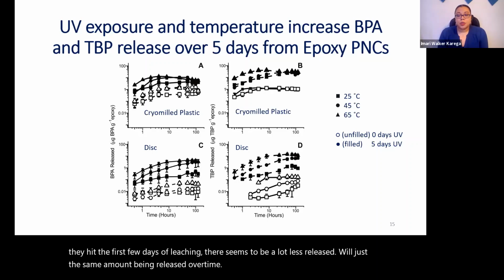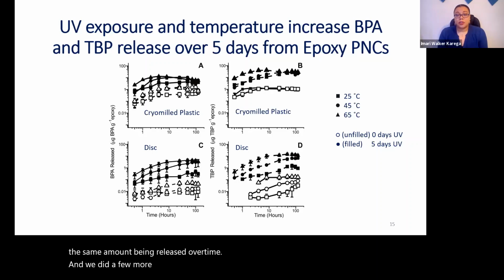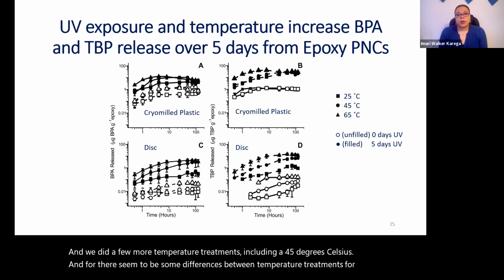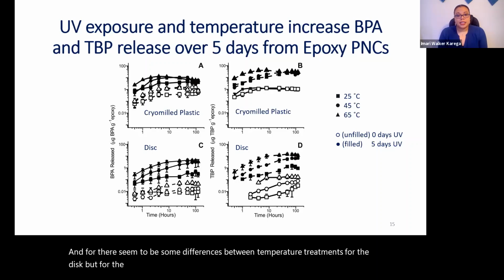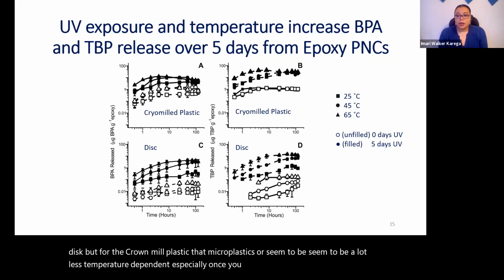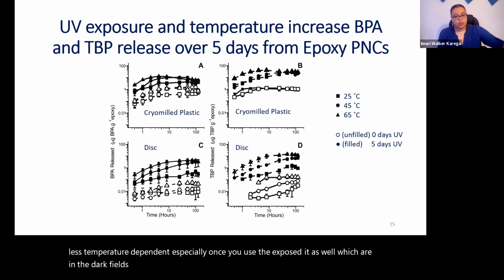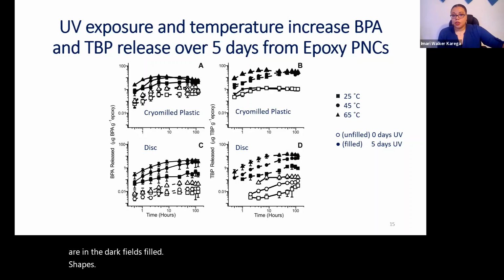We also did a few more temperature treatments, including 45 degrees Celsius. There seemed to be some differences between temperature treatments for the disc, but for the cryo milled plastic that made microplastics, it seemed to be a lot less temperature dependent, especially once you UV exposed it as well, which are the dark filled shapes. So temperature and UV exposure were pretty important.